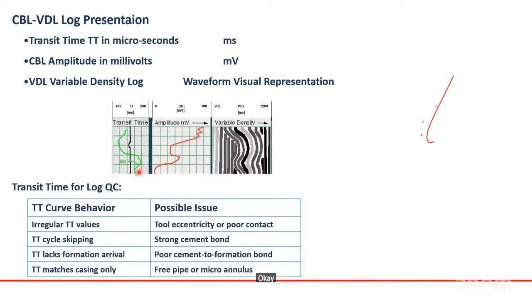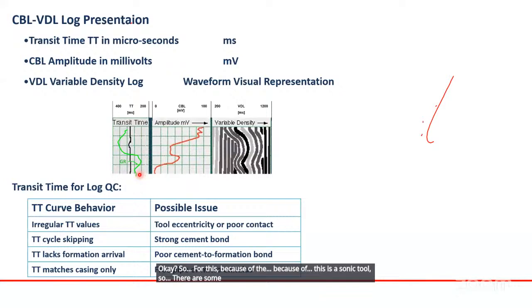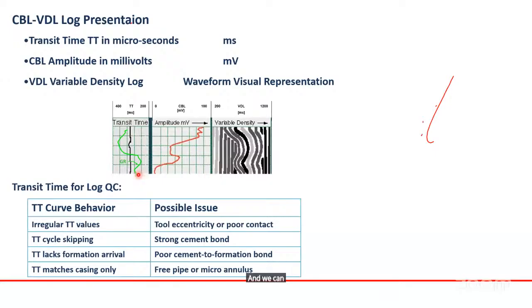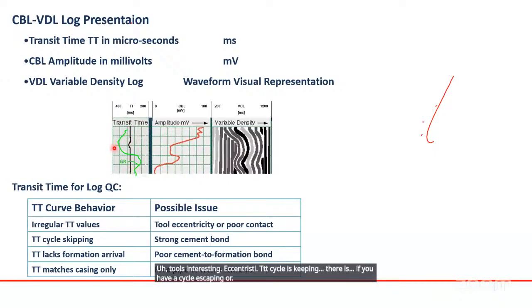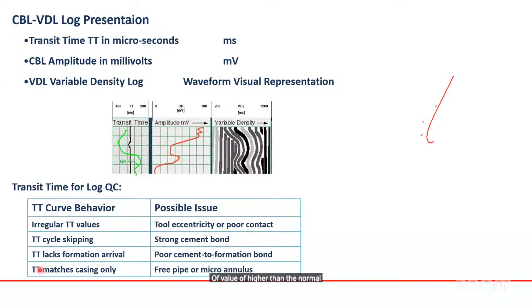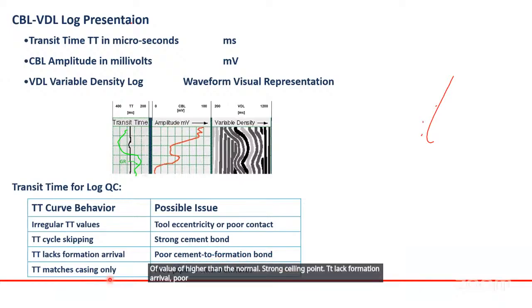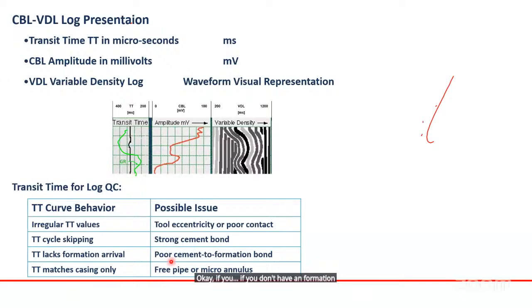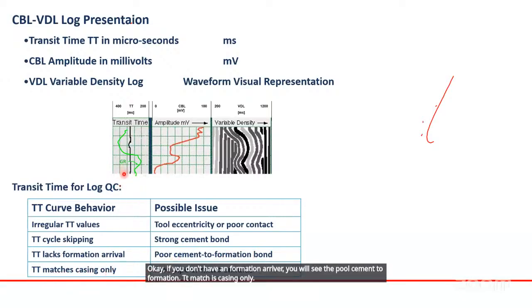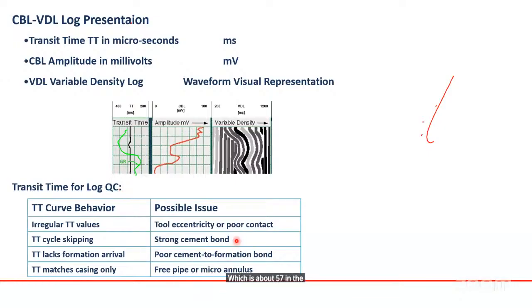Because this is a sonic tool, there are some quality issues that should be considered, and we can capture the quality of the log from the TT curve. If it's an irregular TT curve, it's tool eccentricity or poor contact. There is a problem in the tool eccentricity. With TT cycle skipping, if you have cycle skipping or a value higher than normal, it indicates a strong cement bond. TT lag formation arrival means poor cement to formation bond. If you don't have a formation arrival, you will see poor cement to formation. TT matches casing only, which is about 57 in delta T, means it is free pipe or microannulus.